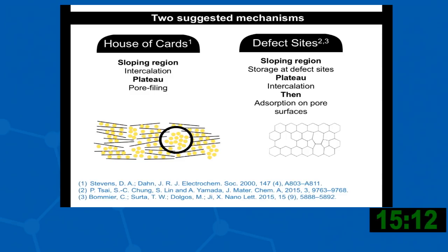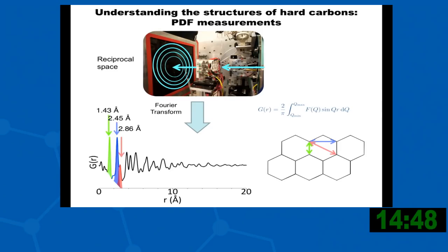Primarily, the group of Jeff Dahn in very early studies proposed that the sloping voltage was due to intercalation, and the plateau region is due to pore filling, so sodium going in between the carbon particles. And then more recent work by Yamada's group has said that defects are important, and that the sloping region is more to do with storage at defect sites, and the plateau is intercalation. So how can we study this?